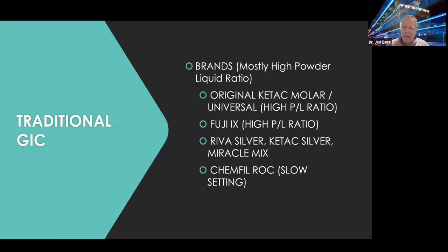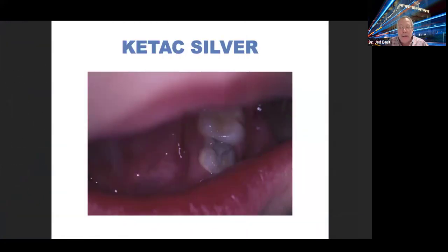I used to use them all the time. It took a lot of talking parents out of the fact that they weren't happy that they weren't white. Let me show you what they look like. And I practiced in Manhattan. So having someone look at their child's teeth wasn't sufficient. They basically had to take their eyeball, stick it in the kid's mouth, and look to make sure that the tooth was aesthetic. This is not aesthetic. But you can also see that in this case, the box is very wide beyond ideal angles for an amalgam or a resin restoration, but they stay intact because of the chemical bonding.